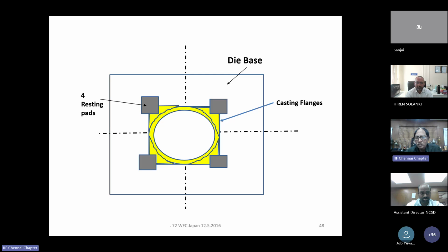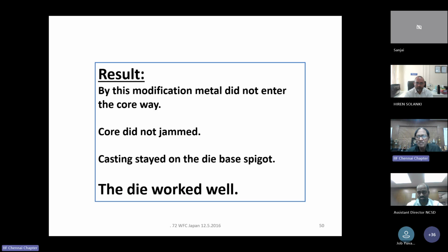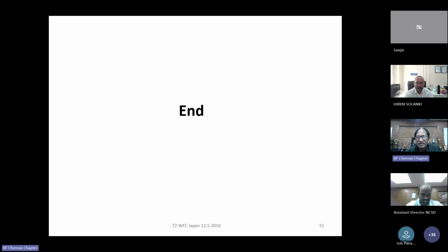To keep the casting on the die, we put 4 pads like this, so that the casting stays on the die base so that we can remove it. By this modification, metal did not enter and the core did not jam. The casting stayed on the die base, and the die worked very well. This was a grand success. This is the end of this 30%.